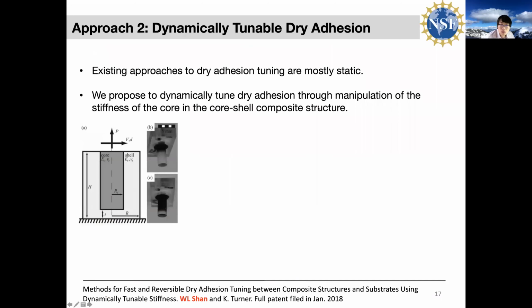The second approach we developed for soft gripping is based on dynamic tunable adhesion. As noted earlier, existing approaches to adhesion tuning are mostly static. So we propose to dynamically tune adhesion through manipulation of the stiffness of the core in a core-shell composite structure. Basically, Kevin Turner and Payne showed earlier that if you insert a rigid core into the elastomeric post, you're going to change adhesion. Now we want to use smart material to change the stiffness of the core.